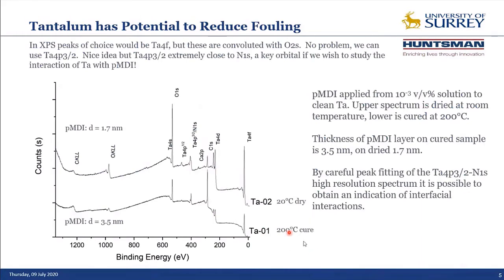The decision was made just to deal with this tantalum 4p3/2 peak, which sits coincident with the nitrogen 1s. We've done all our careful peak fitting around there. The driving force was to make sure that we could deal with both the nitrogen chemistry and the tantalum chemistry from the same depth in the same spectrum.